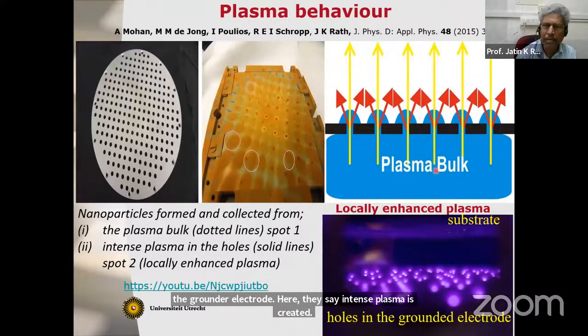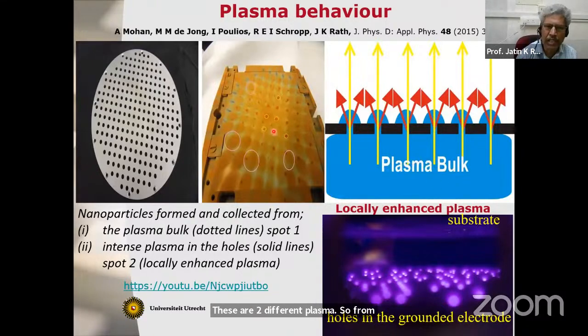So from the plasma bulk, this will come as this one here. These small spots are where the small particles are formed. Whereas this one, from the ground electrode, goes in a conic, divergent way. So that forms the big ones. Mostly the big ones are amorphous, whereas this one is mostly crystalline.